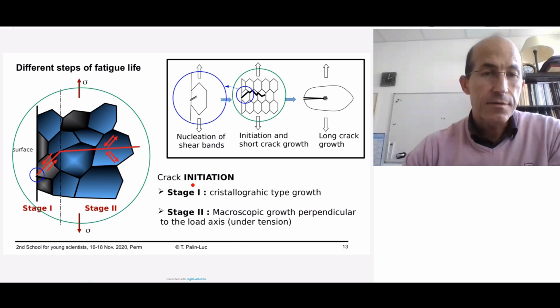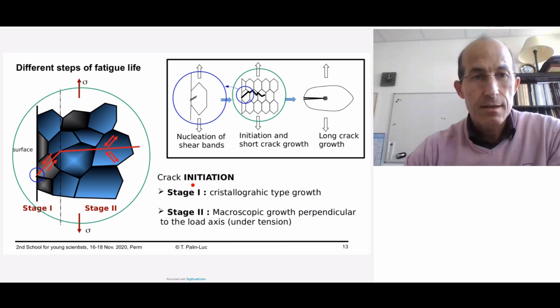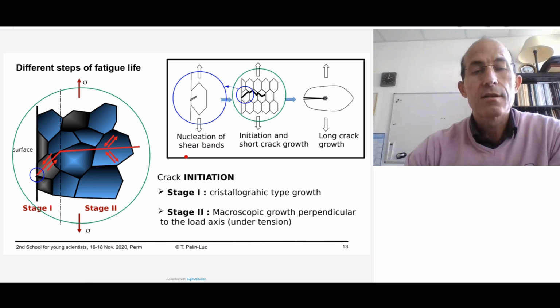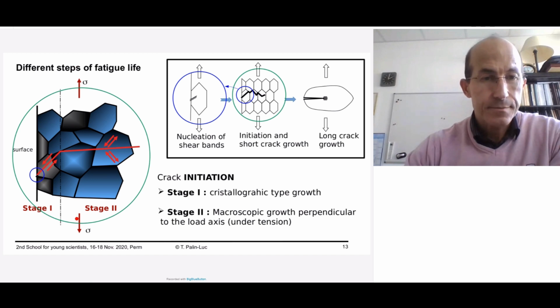What happens after crack initiation? The crack initiation is illustrated here by the nucleation of shear bands, mainly at the surface, or in most cases, as I explained a few minutes ago. If you imagine a polycrystal loaded in uniaxial tension, the first stage, named stage 1 in the literature, is the appearance of a crack due to shear. That is mode 2 of fracture mechanics.